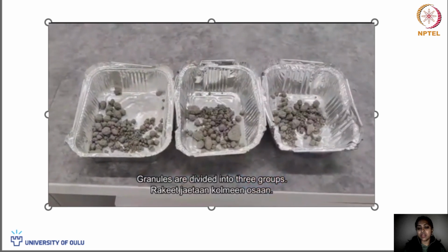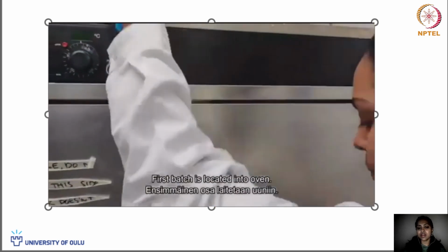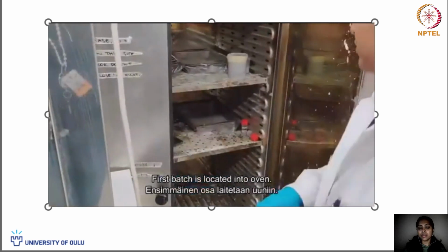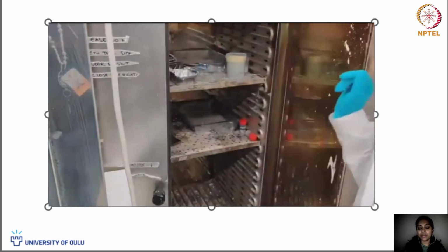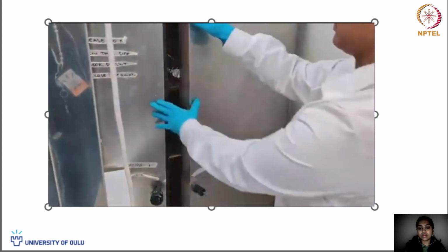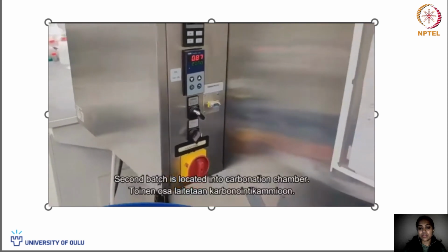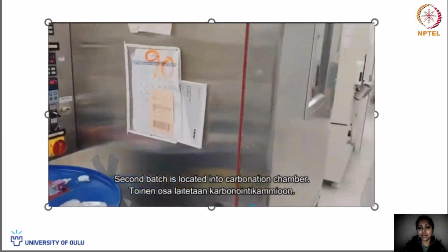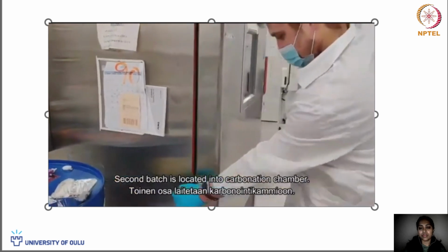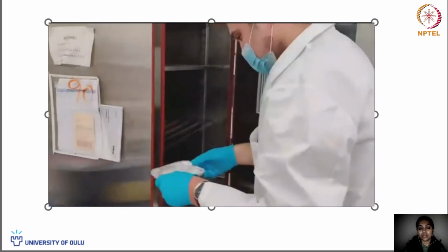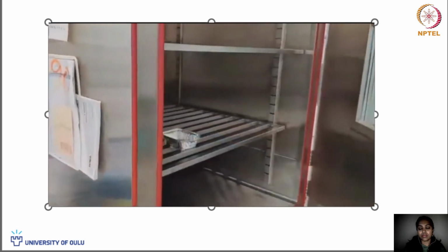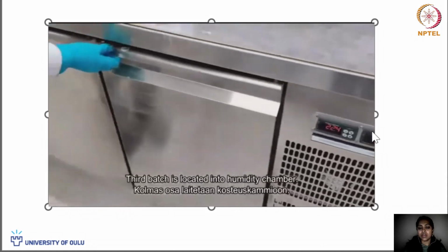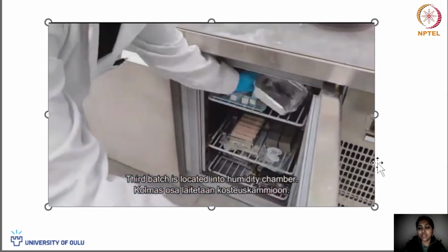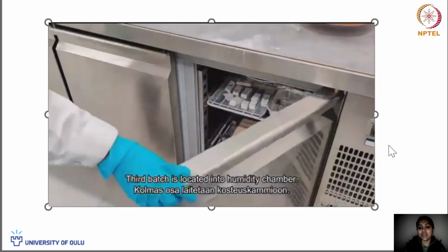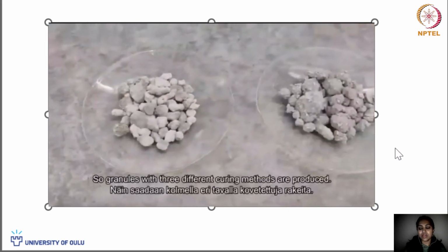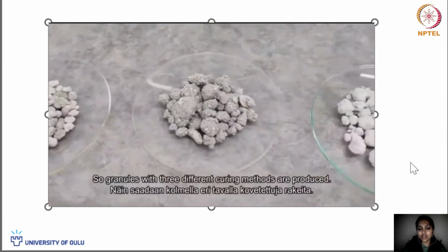And this is separated into three different containers to cure them in different ways. One is in the oven, another one in the carbonation chamber, and the third one in the humidity chamber with 20 degrees of temperature and 100% relative humidity. So this is after curing for 24 hours.